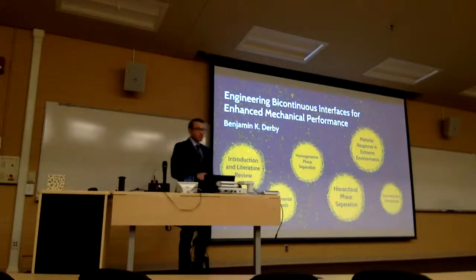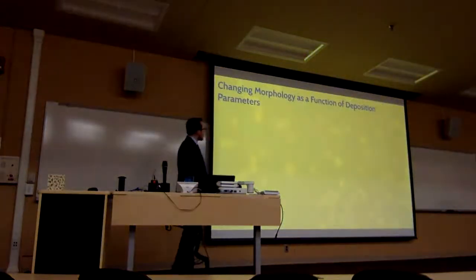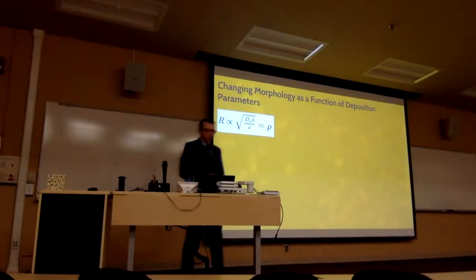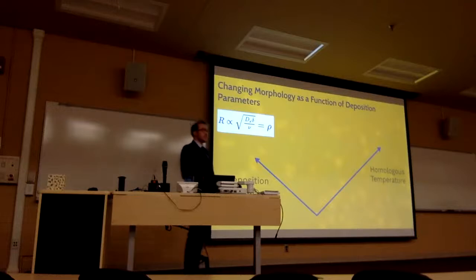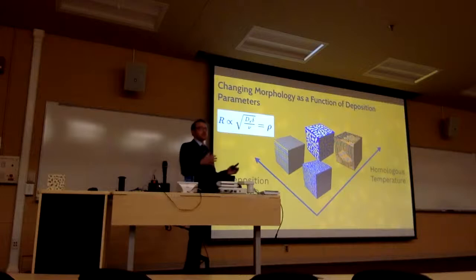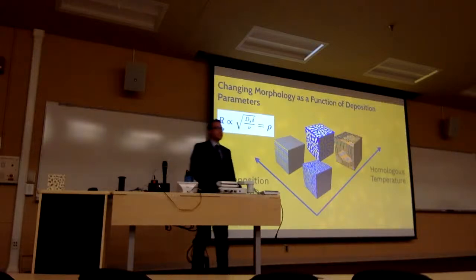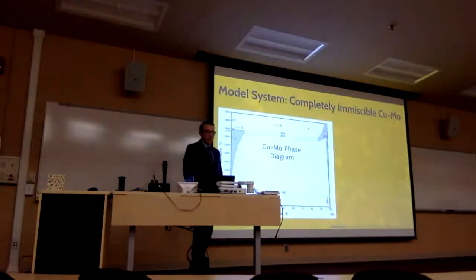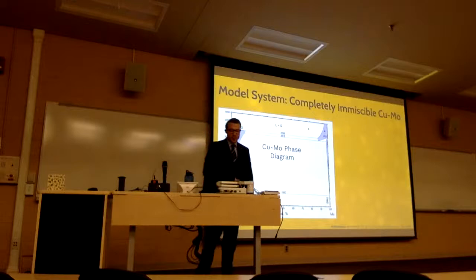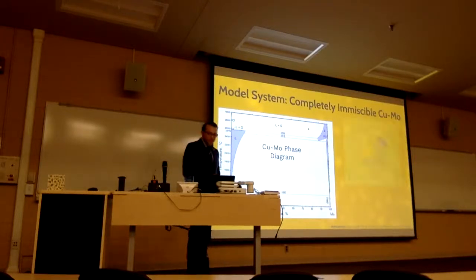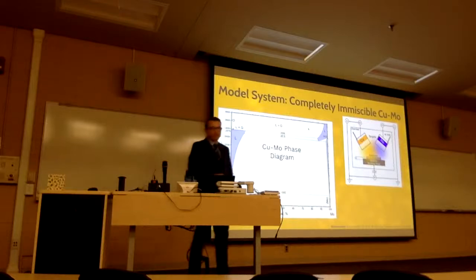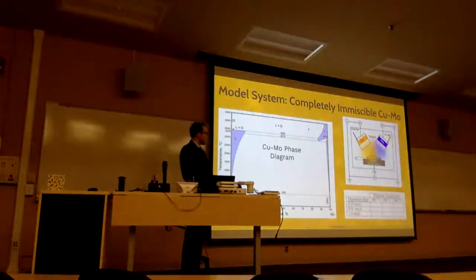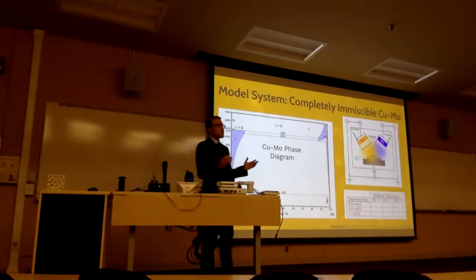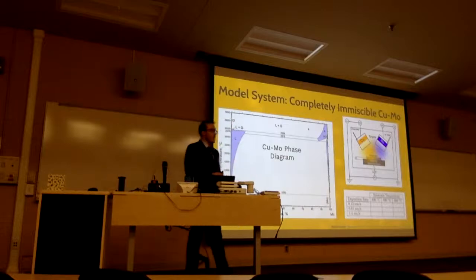And I want to share with you the experimental methods we used to do this study. So we saw this equation here as a function of deposition conditions. The two deposition conditions that feed into this equation are the deposition rate and the homologous temperature, which is the substrate temperature divided by the melting point of the material. And what we could do is deposit a matrix of samples to start seeing where those phase-separated morphologies fit on this morphology map. And so how we did that was we took this ideal copper-moly phase diagram or material system, which is completely insoluble. We co-deposited it onto a heated substrate to force phase separation, and we subjected it to a slew of deposition conditions, or matrix of sample conditions, to start applying where those morphologies would fit on that morphology map.